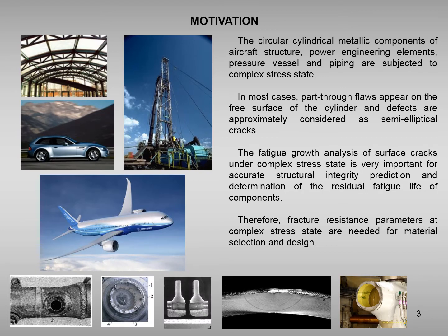Some words about motivation of our study. The circular cylindrical metallic components of aircraft structure, power engineering elements, pressure vessels, and piping are subject to complex stress state. In most cases, flaws appear on the free surface of the cylinder and defects are approximately considered as semi-elliptical cracks. The fatigue growth analysis of surface cracks under complex stress states is very important for accurate structural integrity prediction and determination of the residual fatigue life of components. Therefore, fracture resistance parameters at the complex stress state are needed for material selection and design.